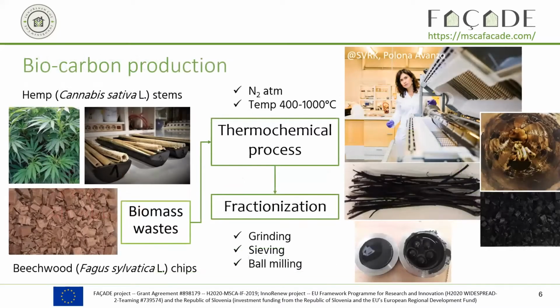UV stabilization. So what do we call biocarbon and how do we produce it? Biocarbon can also be called biochar, and we call it one way or the other depending on the application. So here I chose to call it biocarbon. This is produced from waste and from byproducts. In this project, we considered several sources of biomass. The first one is hemp stems, because in Slovenia, hemp is mainly grown and used for cannabidiol application, which uses only the flowers, and the rest, so 2 to 4 meter high stem, is considered as a waste. So we would use this.